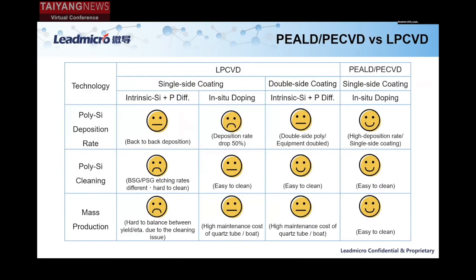This page is a summary between the LPCVD and PECVD methods in terms of polysilicon deposition rate, polysilicon cleaning, and mass production. As we can see here, for the LPCVD method, single side deposition with phosphorus diffusion, we will have a yield issue, and polysilicon cleaning is difficult due to the different BSG and PSG etching rates.